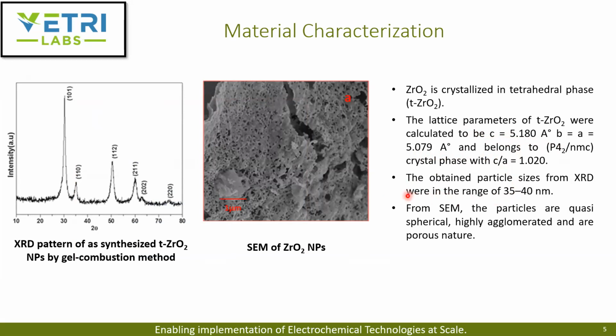And then they did the SEM characterization, and from the SEM they can see an agglomeration of the zirconia oxide nanoparticles, and they attribute that this could be due to the preparation method they employed. They're also porous, because in the combustion there will be gas evolving, and so they create pores in the substrate.